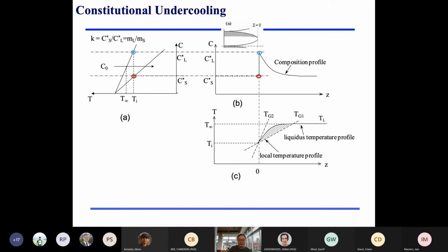So when we grow a crystal, what will happen? Essentially this will be the controlling equation, because solid and liquid have different chemistry, and you grow at this velocity. Those are the concentration differences. Essentially, those solute atoms will be pushed from the interface into the liquid phase. So your liquid phase will have high concentration there. Because the liquid phase is determined at this point, you have a concentration jump at the interface, and this will decay away. This normally decays by a diffusion process, either through solid or through liquid phase.